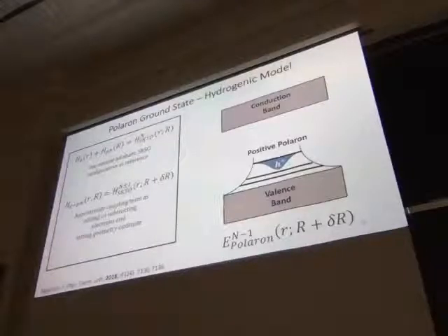Right. So we're just trying to isolate, if we do see emission from these states, whether it comes from the positive polaron or negative polaron. So we just do this to be systematic. Intentionally exclude the possible polaron and look for pure positive polaron, pure negative, because the next step is to see if they can coexist. Technically, do you introduce background charge to make sure everything is what we want? It is included in the software package.